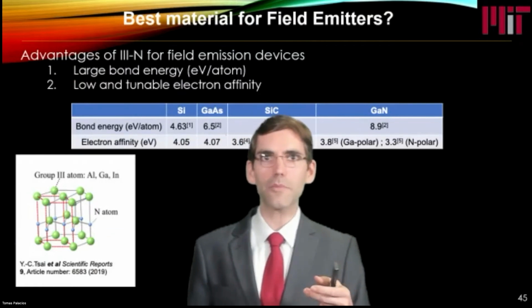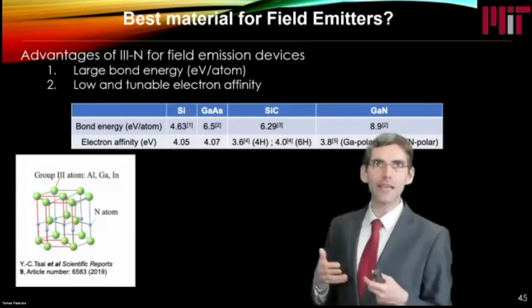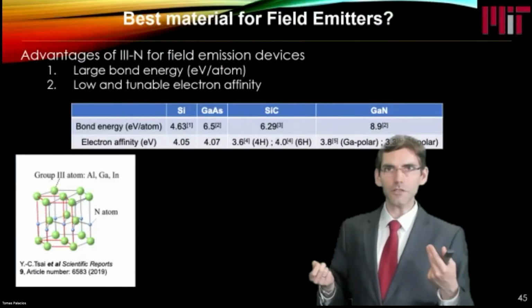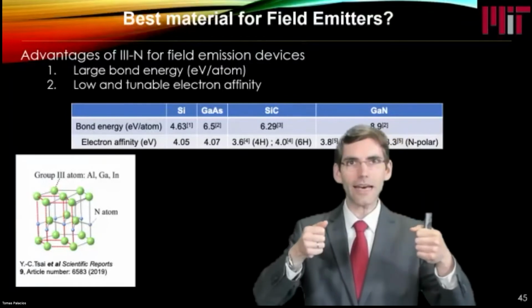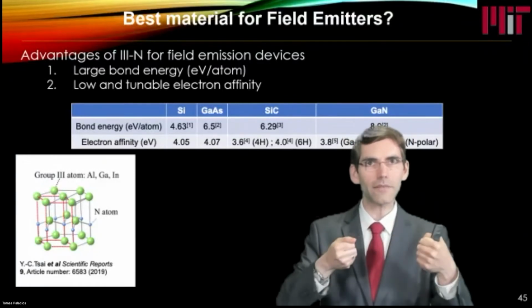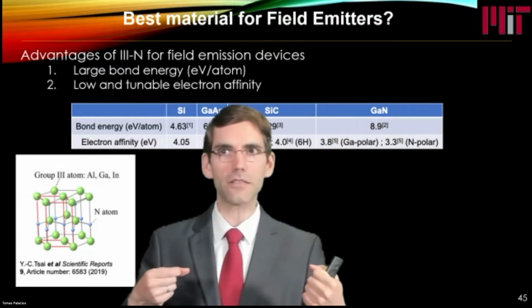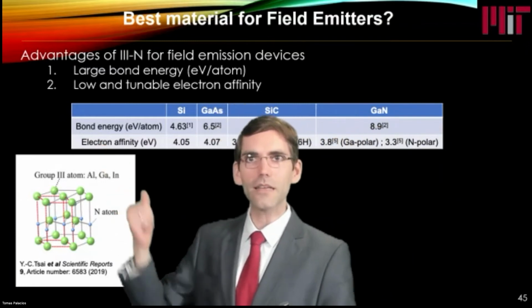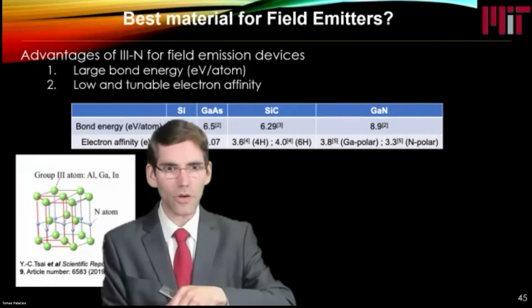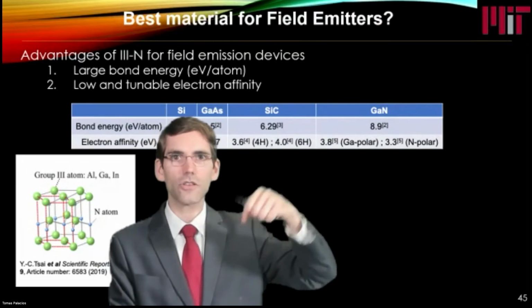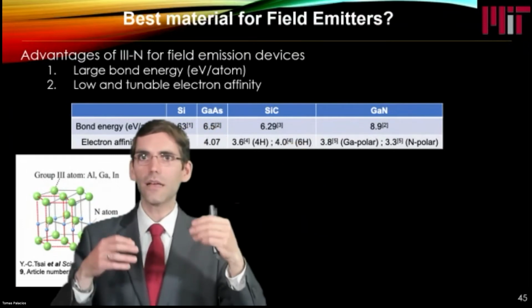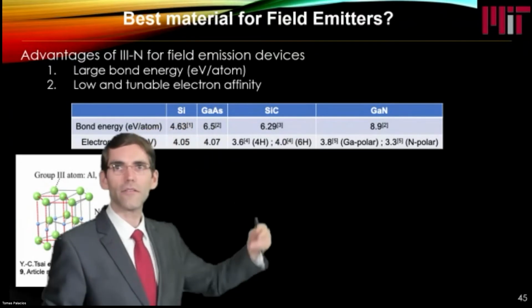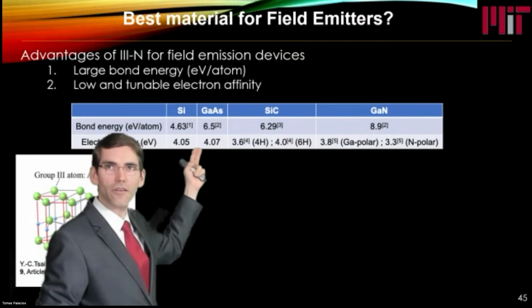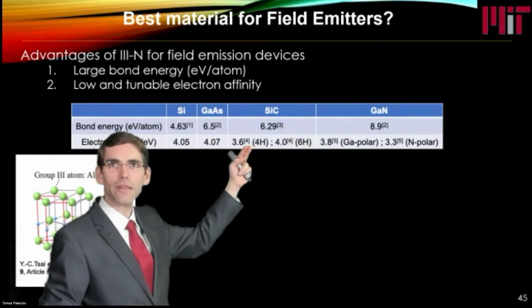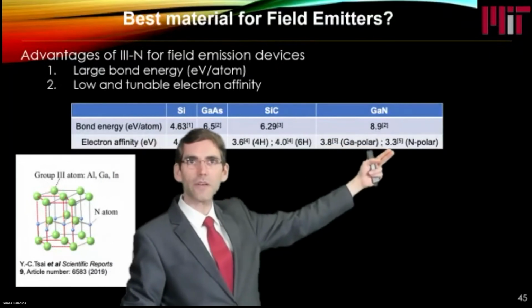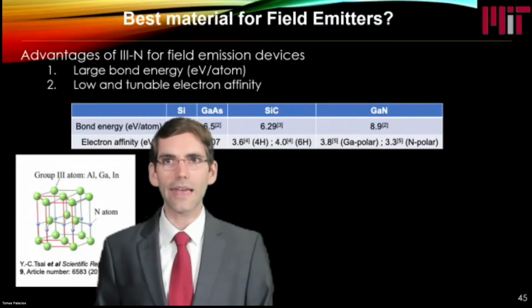So, as I mentioned, gallium nitride happens to be the best material to try to build these field emitters because of two reasons. The atoms in gallium nitride are bonded very strongly to each other. The bond energy is very, very high, so these devices are very robust. On top of that, the electron affinity in a semiconductor is related to how easily you can remove electrons into vacuum, and you need as low an electron affinity as you can. Silicon has 4.05 electron volts, silicon carbide 3.6. In gallium nitride, nitrogen phase, you can go all the way to 3.3 electron volts in electron affinity.